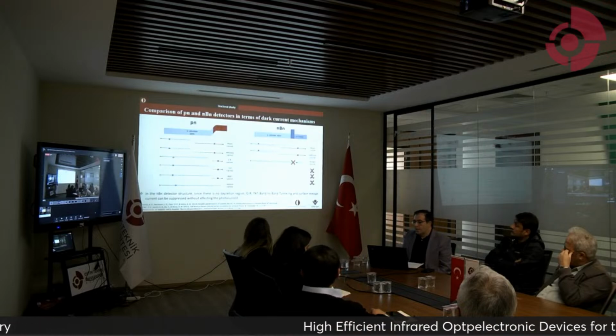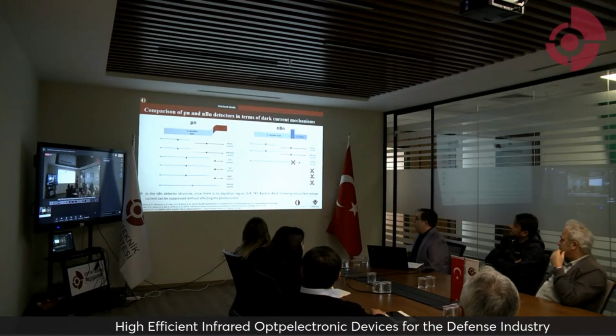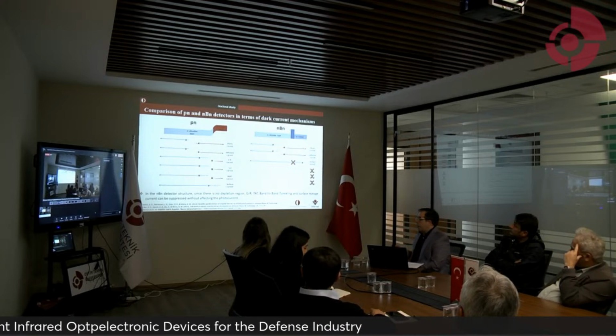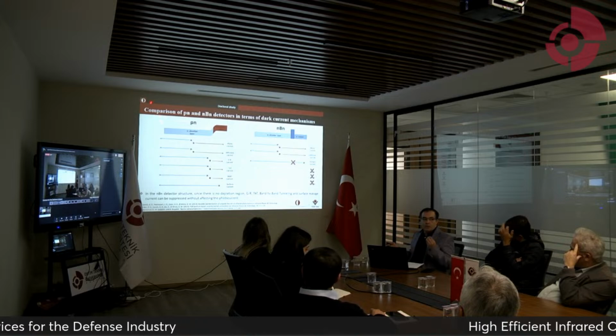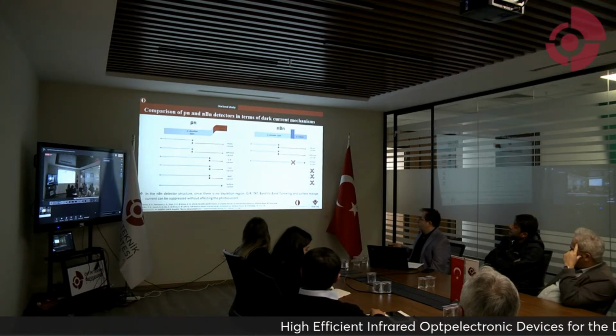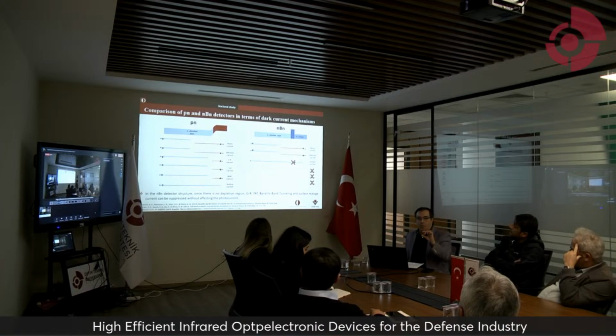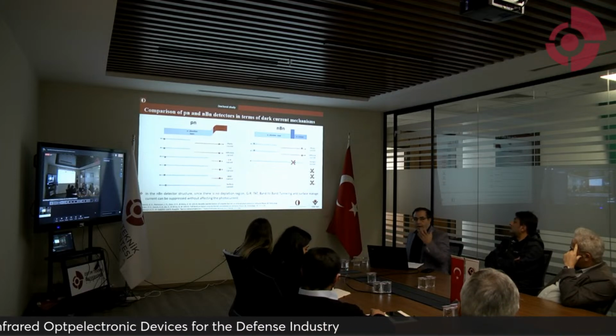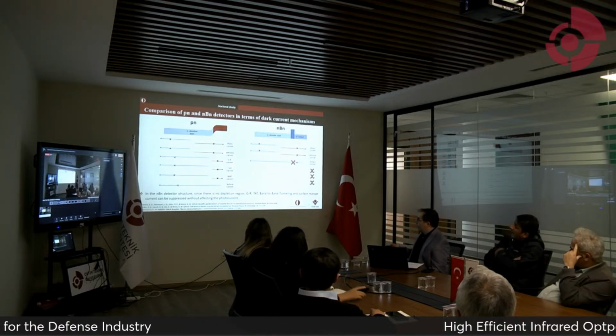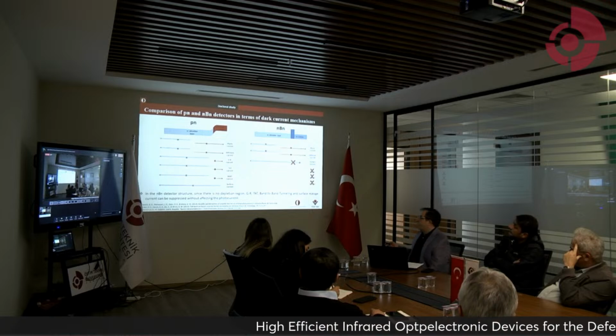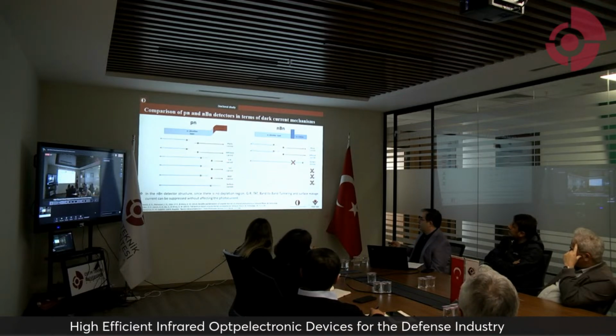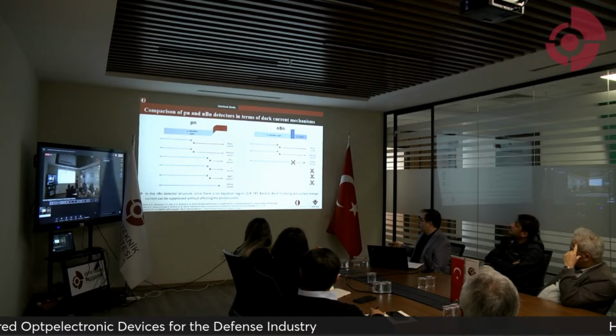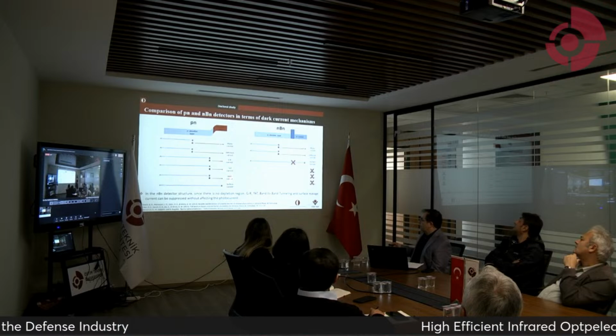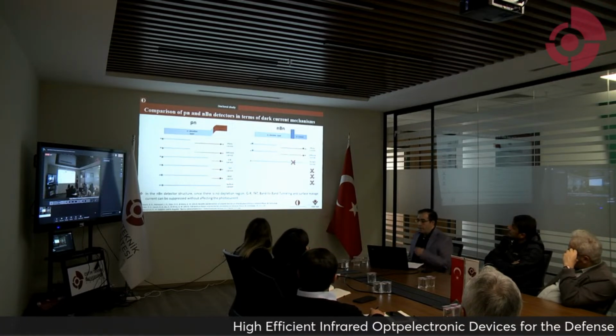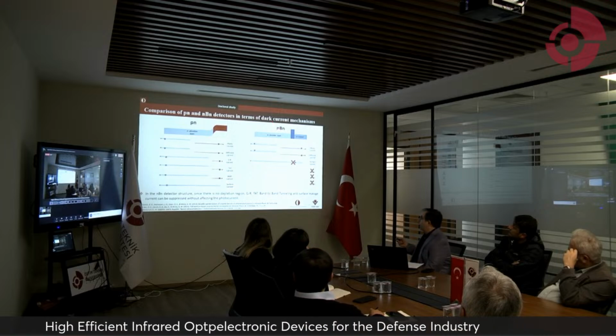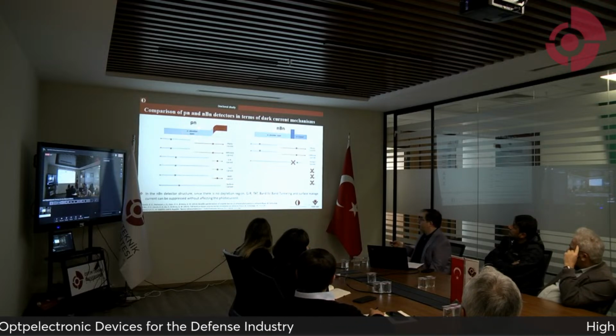First, I would like to mention my doctoral study. Most optoelectronic devices are based on a PN junction structure. But with this kind of structure, when you decrease the bandgap of the device, if you want to see the infrared region, the dark current mechanisms, meaning the noise, can be greatly increased. For example, GR current, generation-recombination current, trap-assisted tunnel current, band-to-band tunnel current, and surface current. And then the NBN structure was developed as an alternative to the PN junction diode.